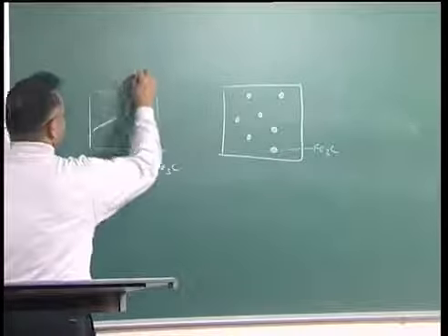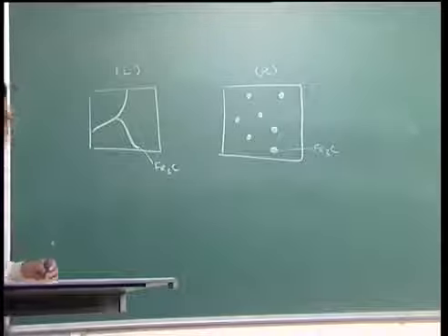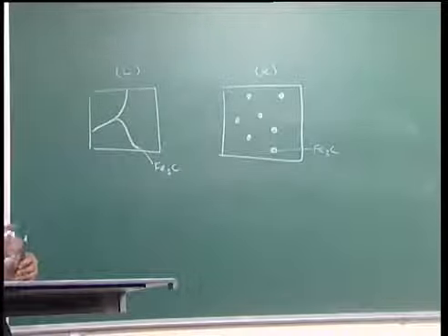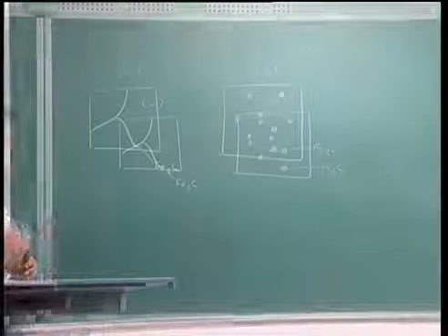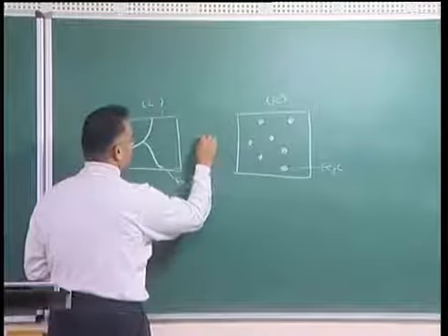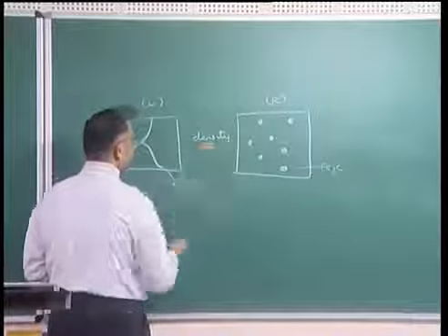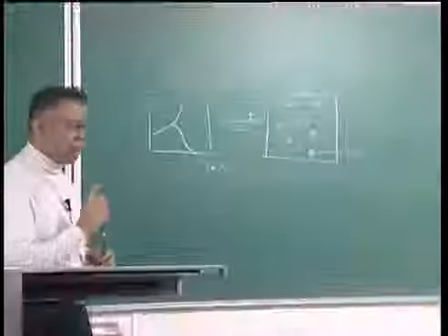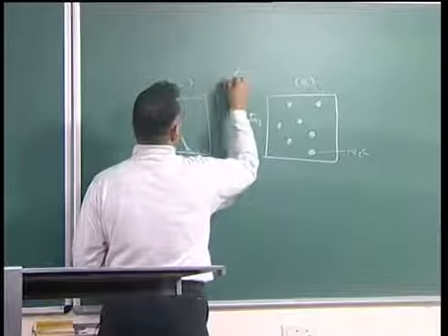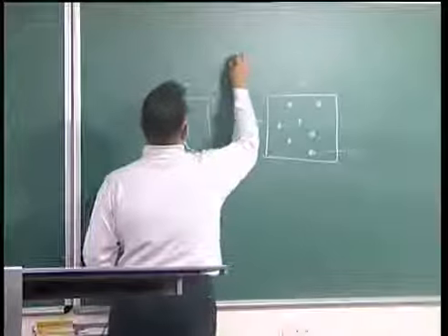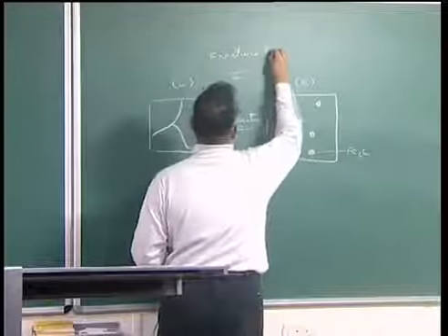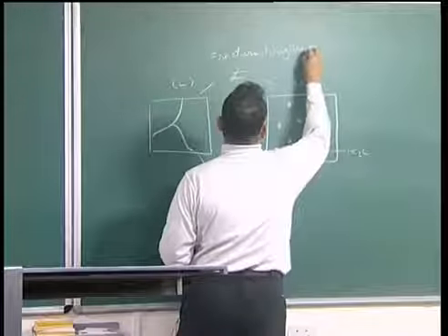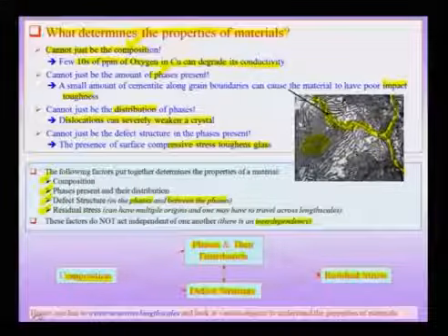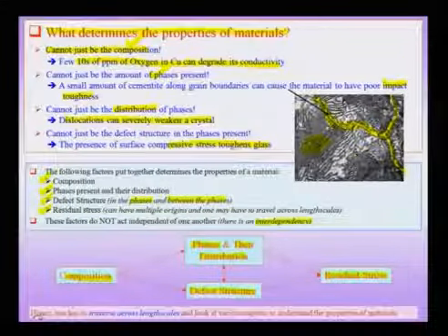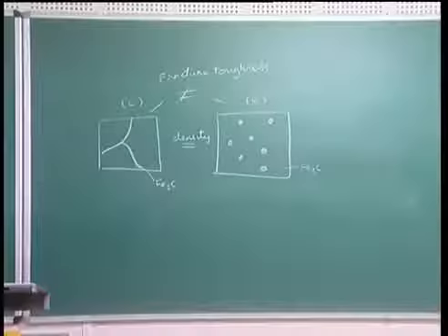So, there is a figure on the left and a figure on the right. The volume fraction of cementite is considered to be equal in both cases. Suppose I am talking about a structure insensitive property like density, then I would notice that the density of these two would be equal. Suppose I am talking about a microstructure sensitive property like fracture toughness, then they would be different for these two. Therefore, I need to clearly understand that the distribution of phases is going to change my microstructure dependent properties, but will not change my microstructure independent properties.